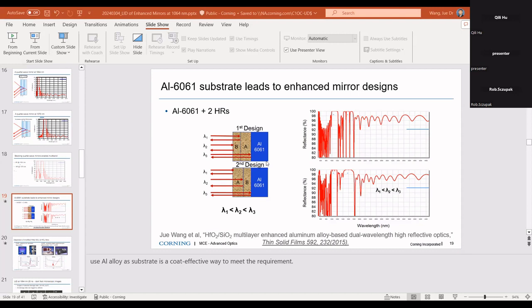What do we do? We find larger nodules, and then make a cut to determine what the composition is, right? Is anything associated with the substrate material? In this case, we do see the seeds using EDS, basically X-ray spectroscopy. You can get the composition information. In this case, we see it's basically magnesium and aluminum as seeds.